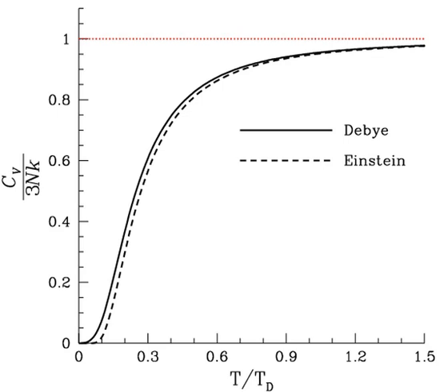However, Brillouin scattering experiments with neutrons and with X-rays, confirming an intuition of Yakov Frenkel, have shown that transverse phonons do exist in liquids, albeit restricted to frequencies above a threshold called the Frenkel frequency. Since most energy is contained in these high-frequency modes, a simple modification of the Debye model is sufficient to yield a good approximation to experimental heat capacities of simple liquids.